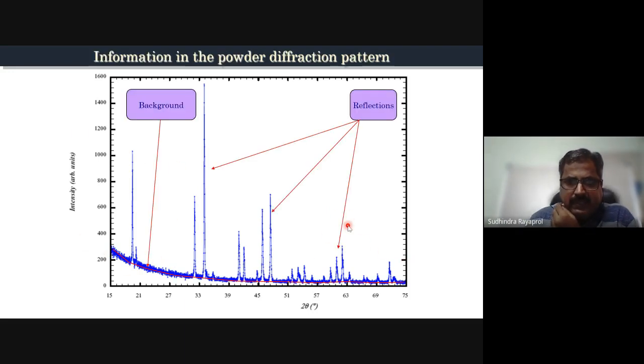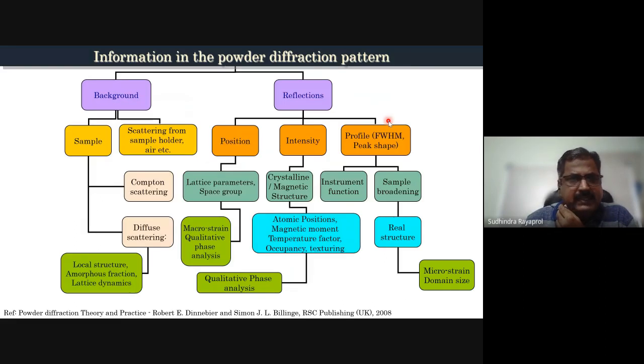Okay, so it has what? It has something called background. It has something called reflections. Now, if you look at them carefully, they contain a lot of information within them. The background can be because of the sample, which means it can be from the Compton scattering or diffuse scattering. If you do local structure or amorphous fraction, you can understand what type of scattering it is. The background can also be from the sample holder. So it is important to distinguish between these two using the proper software tool.